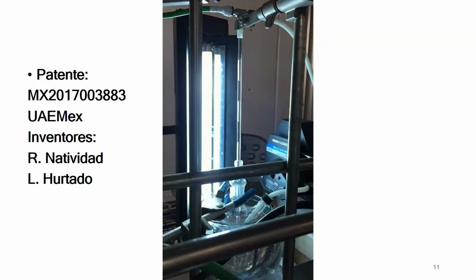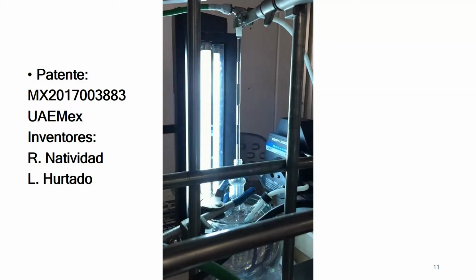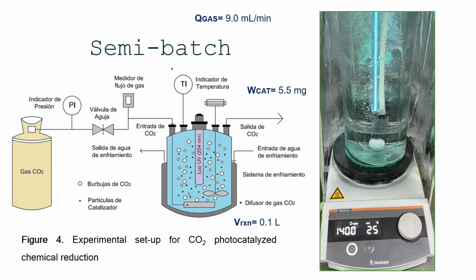There is also the proof of the advantage of the reactor in terms of selectivity. We have compared the results of this reactor with the typical stirring reactor. So this is the batch reactor, the semi-batch reactor that we use.